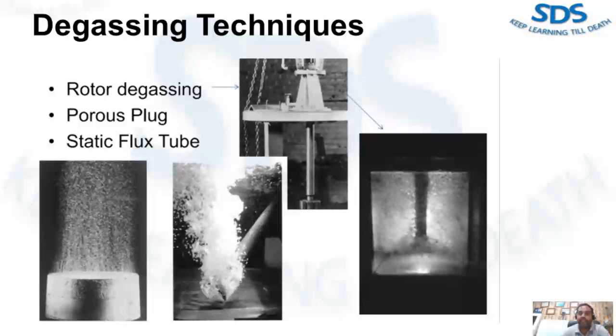Today the most effective degassing technique is to use a rotor degassing device, and you can see in this image rotor degassing produces much smaller size purge gas bubbles than does a static lance. The smaller the bubbles, the greater the surface area and the slower the rate of rise through the melt, which combine to produce higher degassing efficiency. This can be demonstrated in a water model, in which it can be seen that there is a wider swarm of many more smaller bubbles with the rotating device. The same effect can also be achieved, but with less purge gas metal mixing, by using a very fine pore size porous dispenser on the end of a static flux tube.